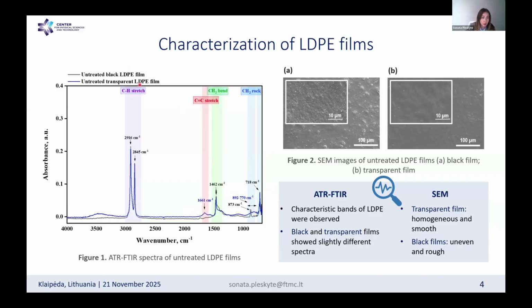And when we are talking about the transparent films, we can see even more spectral changes in this type of polymer. So let me start with this region where we can see carbon-hydrogen out-of-plane bending. Also, we found the appearance of a new peak at 1,661 inverse centimeters, which corresponds to carbon double bond carbon stretching. And then we found the formation of a broad band in this region, which suggests that there are alcohol-containing groups in the pristine LDPE films.